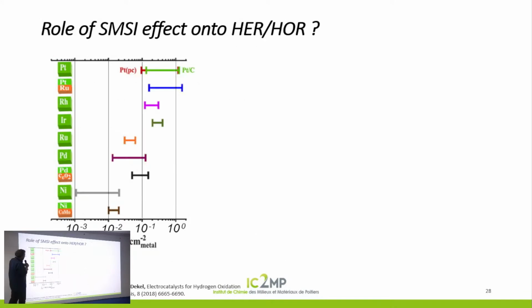So here you see the error bars that you find in the literature, how the activity or the exchange current density may vary according to the nature of the element and also according to this support effect. Some time ago, we published this because we were able to have sp2 carbon. On this sp2 carbon, we photodeposited platinum, and with calculation and measurement, we observed a strong bonding, a hybridization of the orbitals with the sp2 orbitals of the support. And that really gives an interesting interaction on the catalytic site.